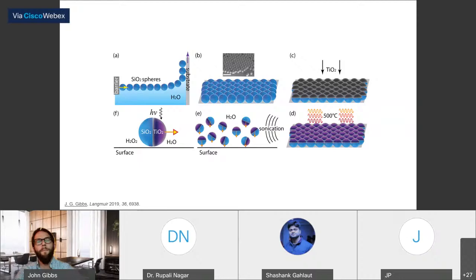And so we have a bath of water, and the lowest energy configuration is going to lead to these being in a close packed monolayer of spheres. They'll float right in the water, and then we can use these barriers to push inward as the substrate's pulling out. The barriers are important because if you don't have them pushing inward, you'll end up getting gaps, and you won't get a nice continuous monolayer over the entire film. So that's a nice process. It's not exactly single crystalline, but it is a monolayer, though you do have some defects in the crystal there.